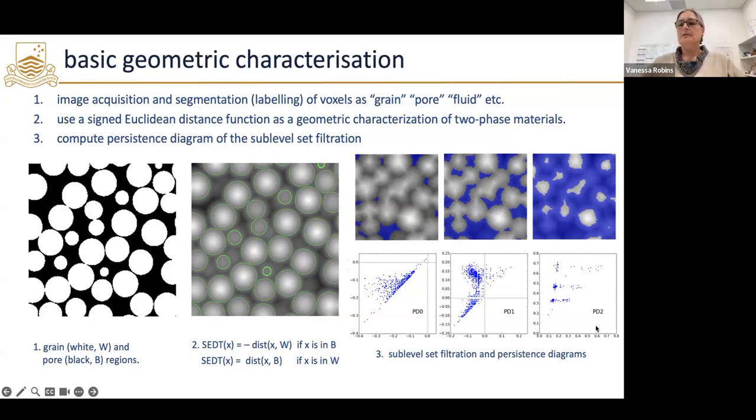And then in the degree 2 persistence diagram, we are capturing information about the grains. So the births are some positive number here, and then the deaths are very distinctive because I have 3 different sizes of grain here. Okay, so these little clumps, their death values are the radii of the 3 different sizes of grain.